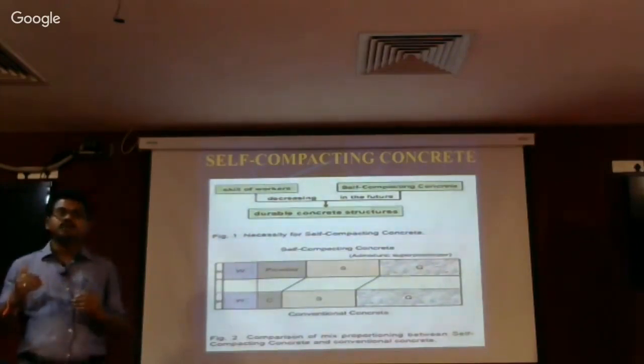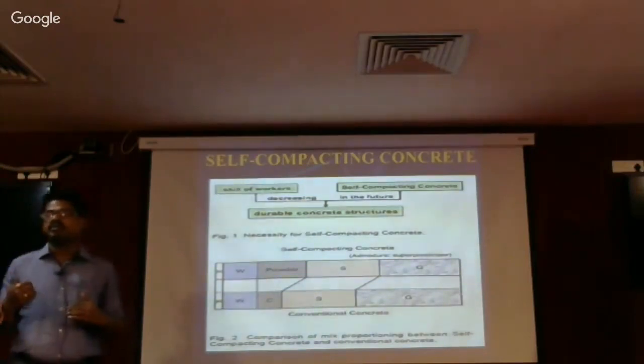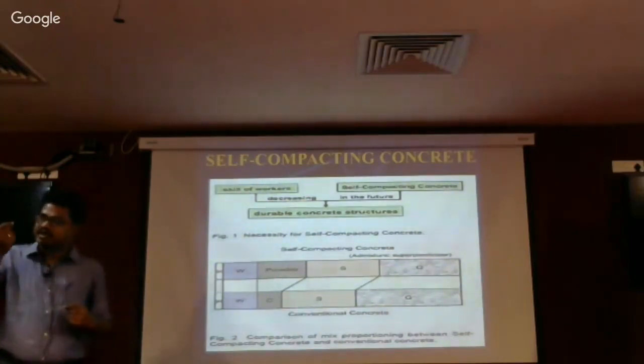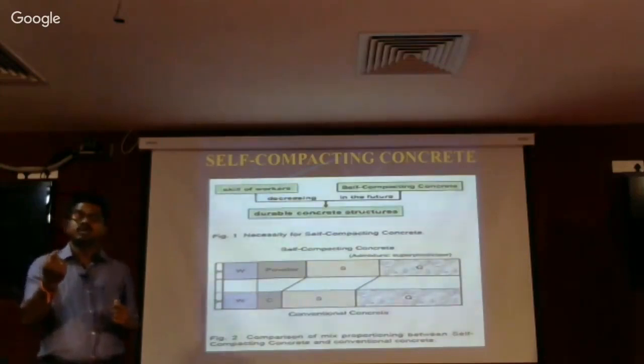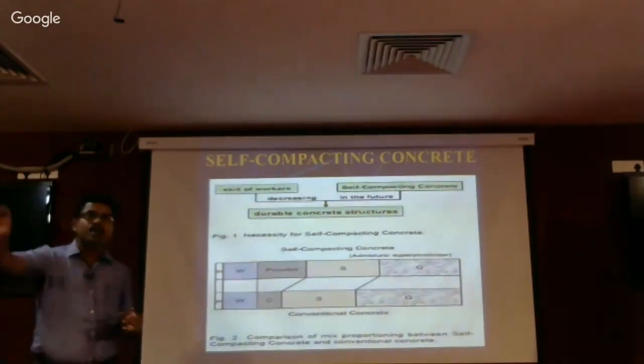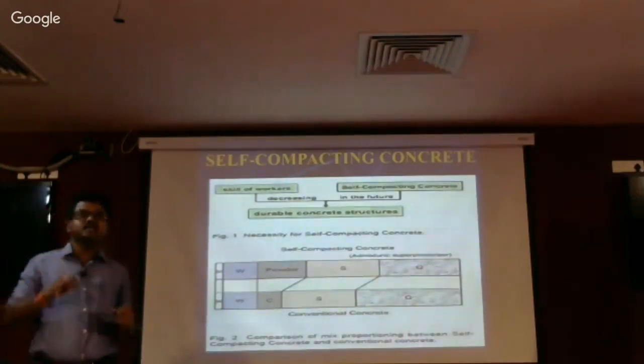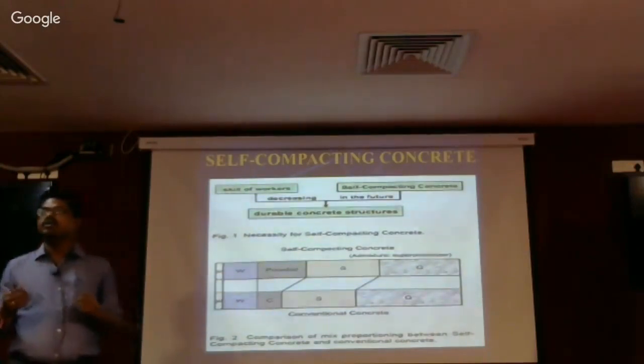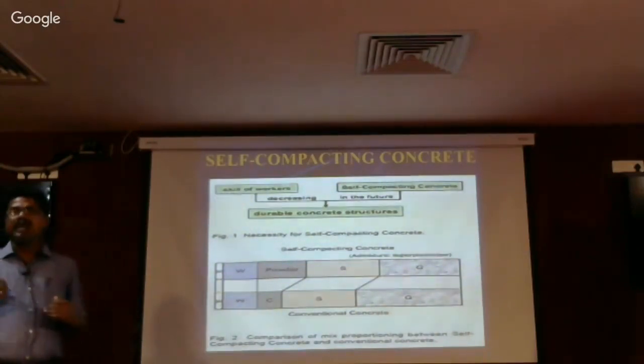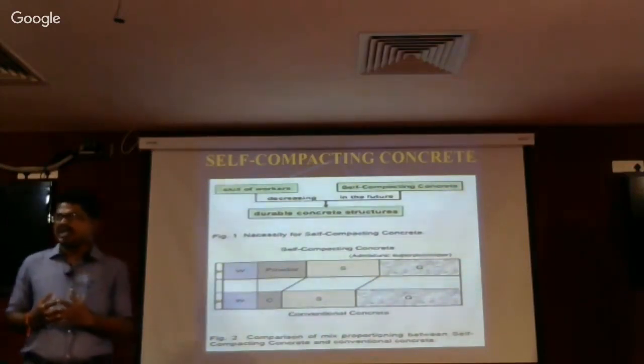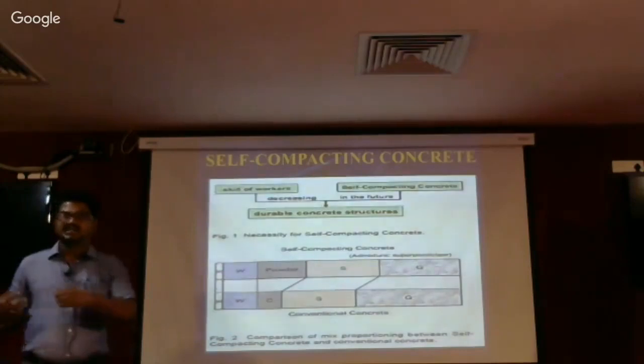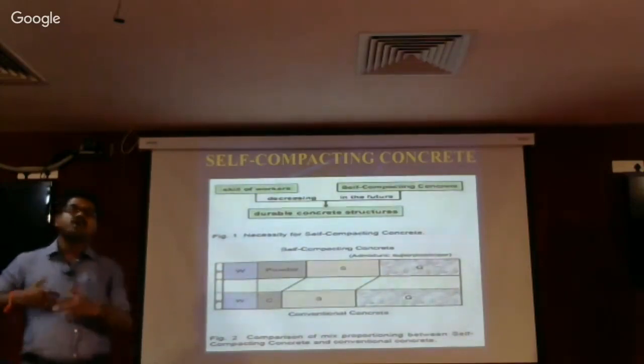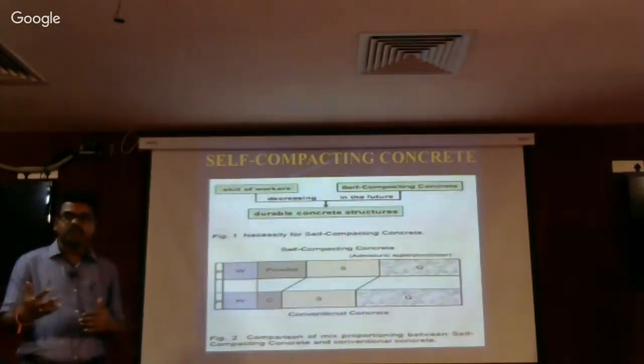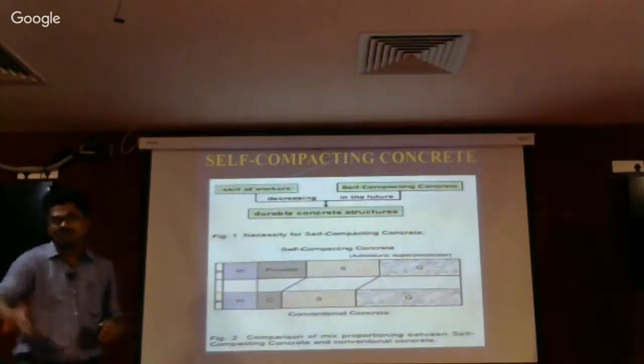High range water reducing admixtures. If I am adding a high range water reducing admixture, even though its quantity is less, it is going to show its effect more in the workability properties and in the strength gain properties. Like that, we are going to add a super plasticizer and viscosity modifying agent, because of viscosity there is a chance of segregation and bleeding. So if you are able to avoid these viscosity problems, then it can flow easily.